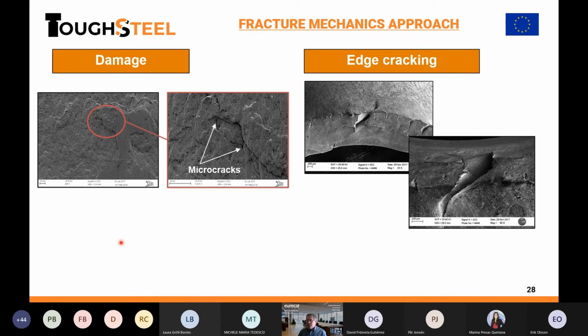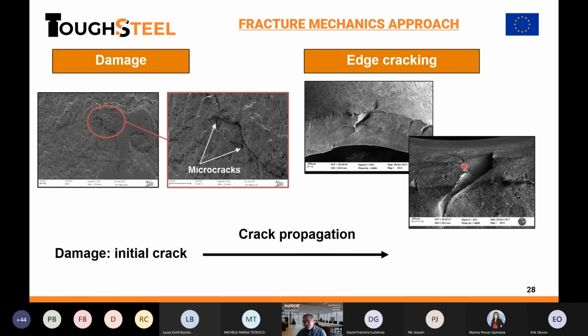Well, fracture mechanics deals with cracks. And we saw in the previous slide that cracks are there when it's about forming of trimmed or punched edges. This is the SEM picture of a cut from a shear edge. We see micro cracks. At the end of micro crack growth, in the part we see the large cracks or visible cracks. So we start from an initial damage, an initial crack. This crack grows and becomes an edge crack. So if crack propagation is the parameter that governs the path from the initiation of the crack to the final edge cracking, fracture toughness is our property. Toughness is the property we have to measure.